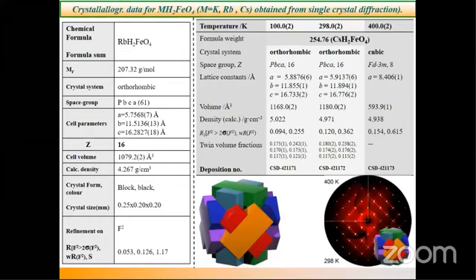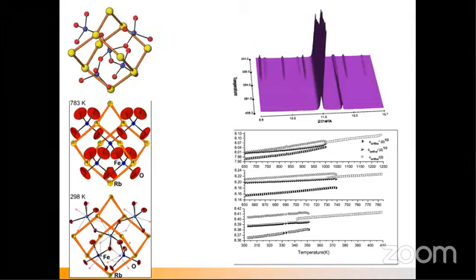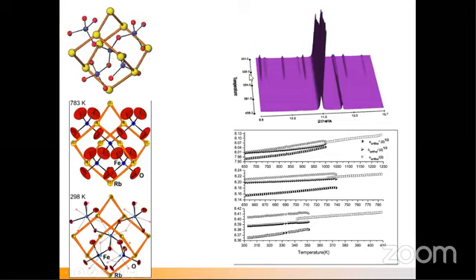This is a single crystal structure that we have grown and solved, and these are the results. Another good thing is to see the thermal ellipsoid of the oxygen. For example, if the metal-oxygen-metal bond is vibrating or rotating, the oxygen thermal ellipsoid will be big. But when it's not rotating, it will be a very well defined circle, as shown in the lowest picture on the left. At high temperature, the ellipsoid gets bigger. Through crystallography, one can calculate the B-iso thermal parameter, and the higher the value, the more directly it depicts that the oxygen is moving. So this is one of the methods to check.